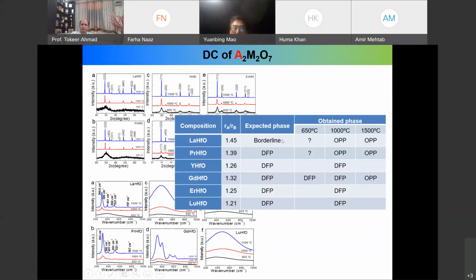So this is what we try to summarize. Expected, based on that formula, right? If the ionic radius is below 1.46, it will be the disordered fluorite structure, right? For this one that's here. And then, from the direct calcination, we can see that for this one, we actually don't know what the crystal structure is. But after 1,000 degree calcination, we got the ordered pyrochlore structure instead of the borderline, and this also pyrochlore structure instead of the expected fluorite structure, right? So this is the synthesis through the direct calcination of the precipitate.